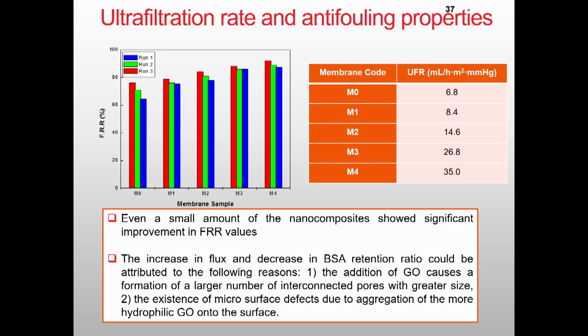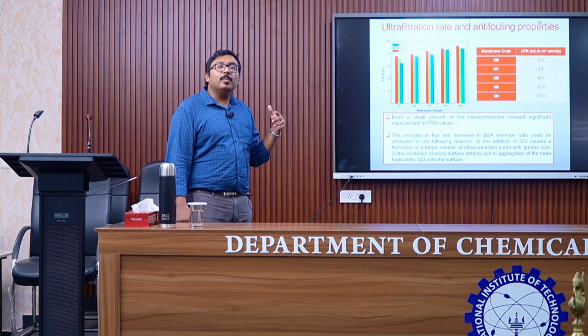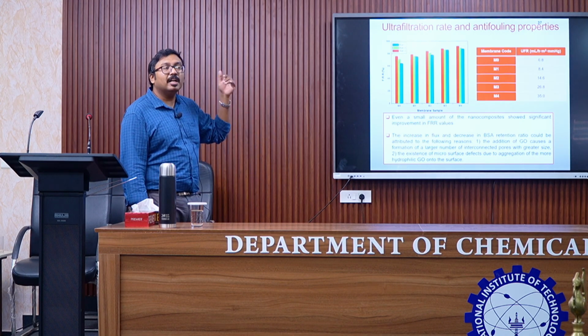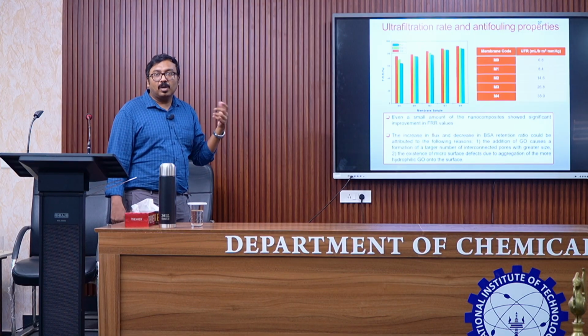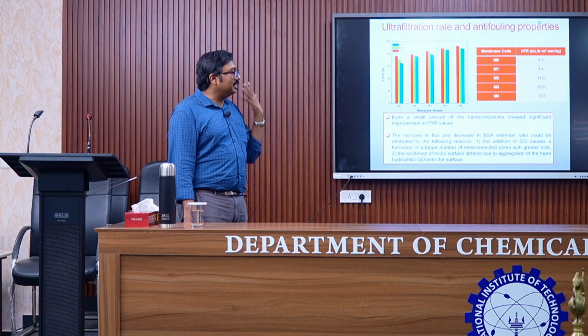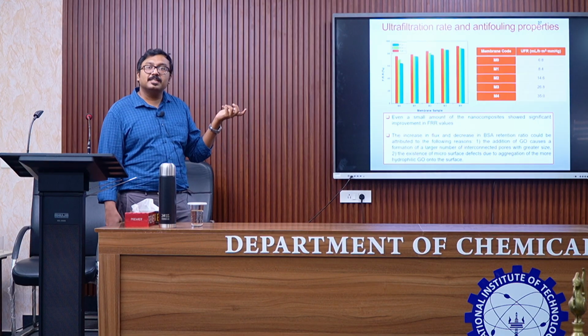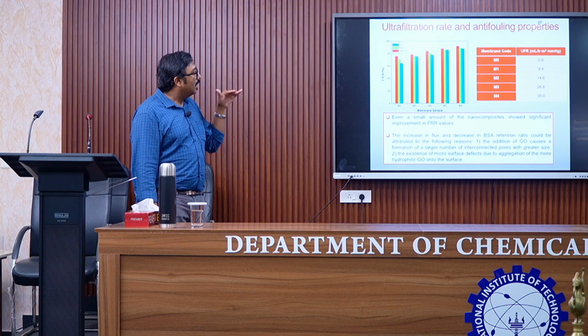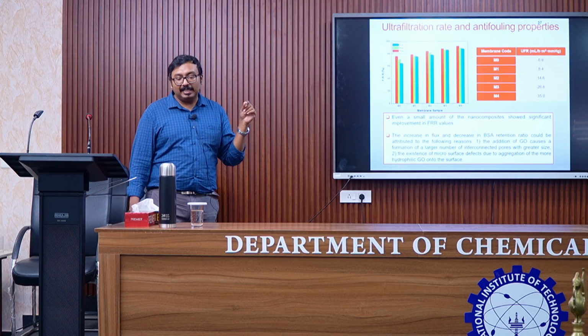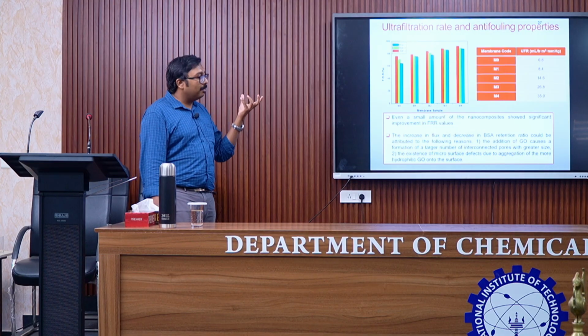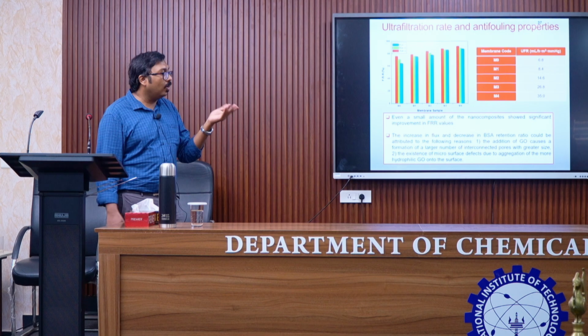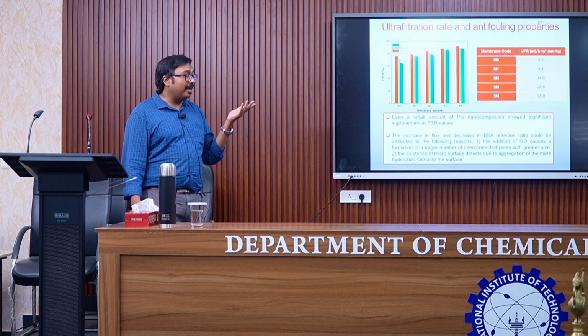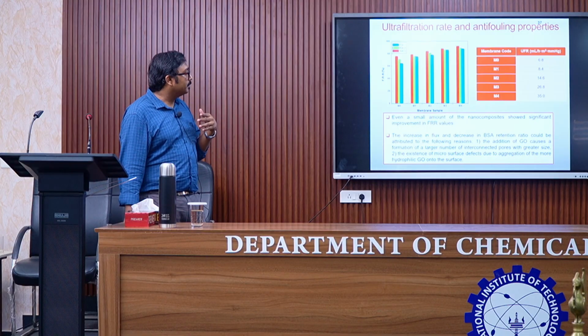So the ultrafiltration rate, that is ml per hour per meter square per unit mm of Hg or mercury. So we can see that on increasing the nanomaterials, the membrane fluxes had increased or the ultrafiltration rates had increased. Again, this is what we were looking for. We want membranes with much higher ultrafiltration coefficients such that they become high flux membrane dialysis. So M3, M4 are above the 20 mark. So the 20 ml per hour per meter square per mmHg is the threshold for classifying it into low or high cutoff or high flux membranes. So these membranes achieve that part.